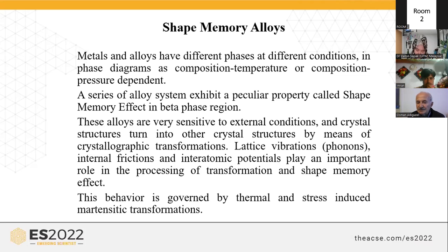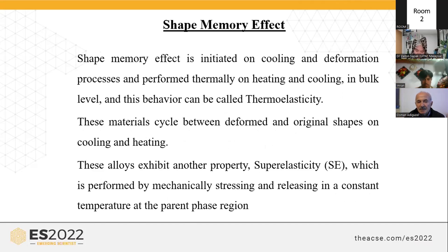Vibrations, phonons, internal friction, and interatomic potential play an important role in the processing of transformation and shape memory effect. This behavior is governed by thermal and stress-induced martensitic transformations. Shape memory effect is initiated on cooling and deformation processes, and recovery is performed thermally on heating.